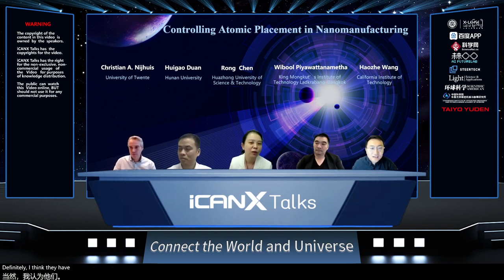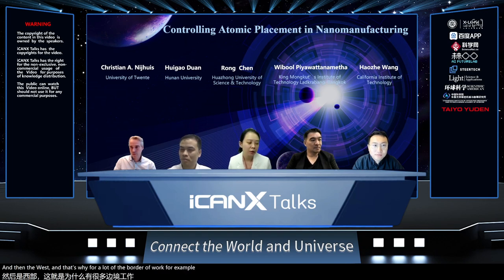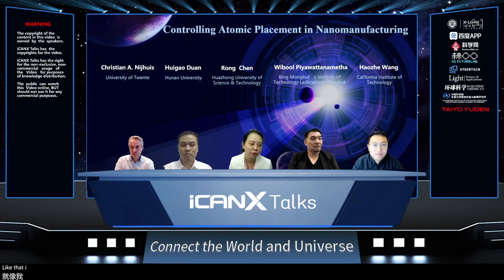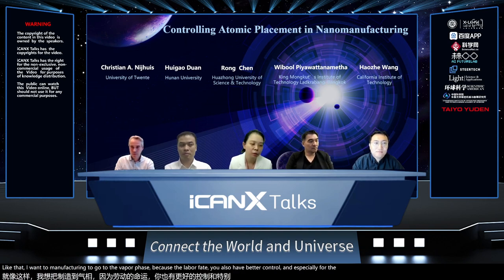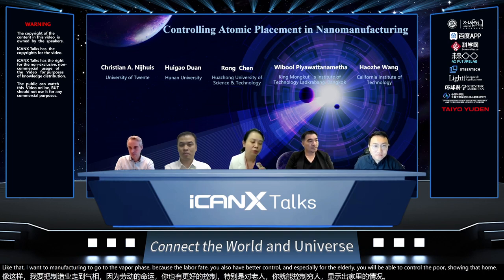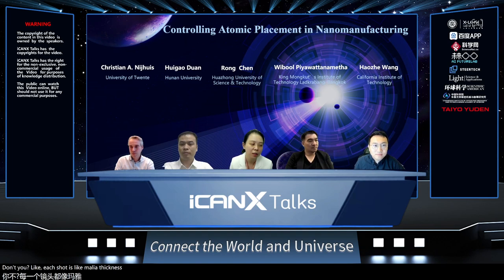Definitely, I think ALD has two advantages compared with the wet methods. First of all, vapor phase processes often have better control than the wet. That's why for a lot of laboratory work, for example perovskite solar cells, normally they run in the lab with wet methods, and then when they want to go to high volume manufacturing, they go to the vapor phase. Especially with ALD, you will be able to control the core-shell down to where each shell is like a monolayer thickness, and it's very uniform. That's one of the advantages.